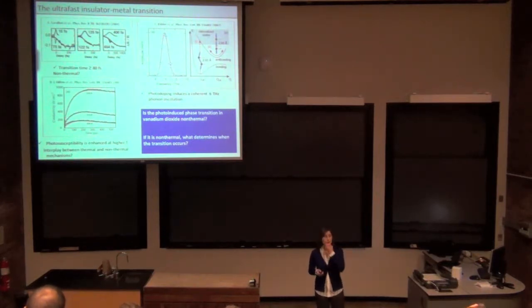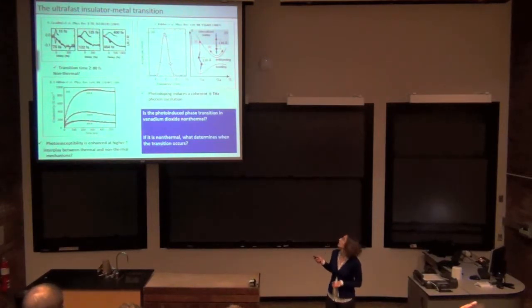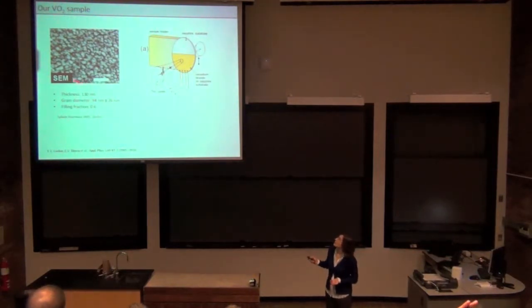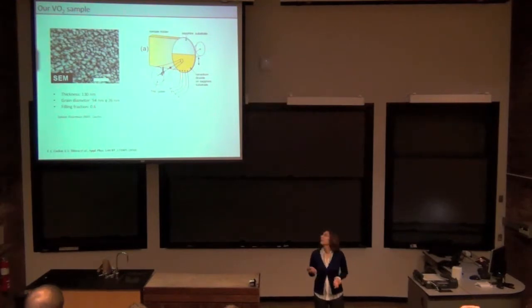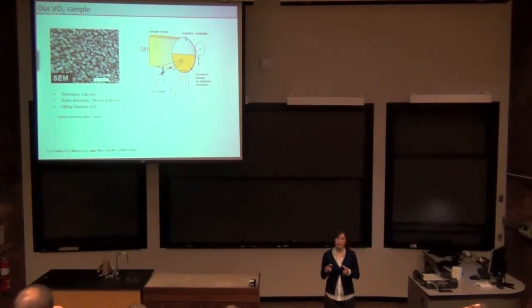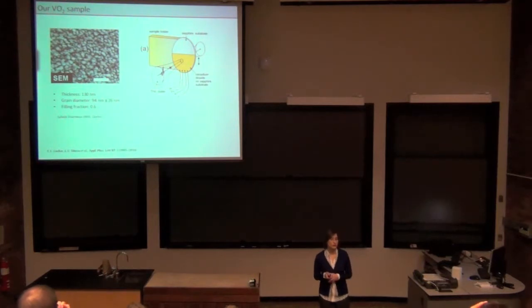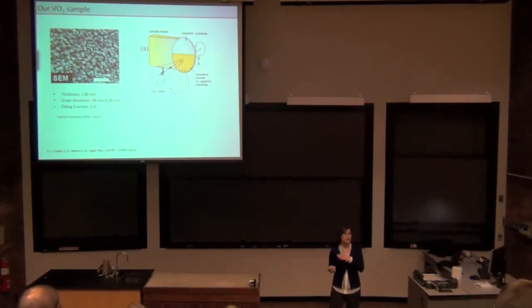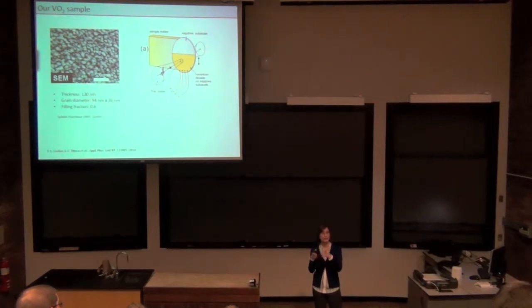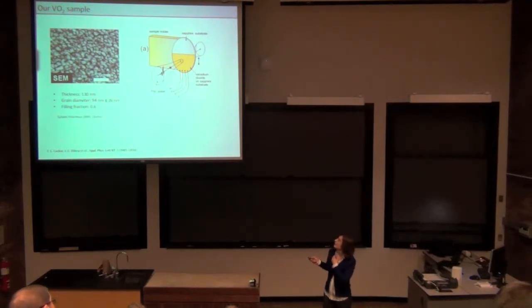But before we can do photo-excited terahertz spectroscopy, or photo-excited transition, we needed to first understand the thermal transition. So what we did, and this is actually the sample that we have, was a nanogranular sample that was grown at INRS in Quebec. The grains are quite large, so we don't actually see any effects from the grain boundaries. The reason why everybody uses granular samples is that single crystalline samples do exist, but upon thermal cycling they tend to crack, so there's just a difficulty using them. The film was 130 nanometers thick.